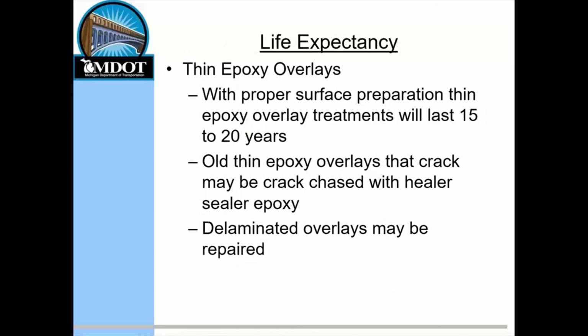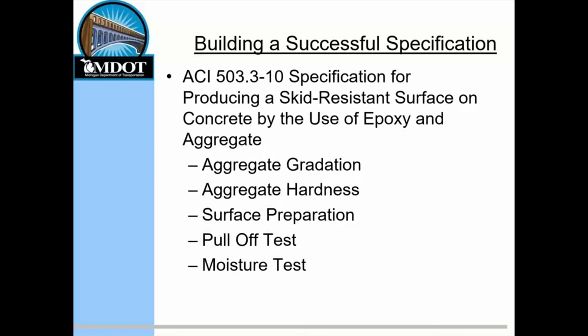The life expectancy of thin epoxy overlays with proper surface preparation, because surface preparation is everything, is 15 to 20 years in Michigan. Some of our older thin epoxy overlays may have some cracks in them. You can repair those by chasing them with a healer sealer epoxy. You can repair delaminations. And then at the end of life, when it's fully polished or the snowplows have removed enough of it, we're having a lot of success with milling off the old thin epoxy overlay and replacing it with another one. We really like our specification in Michigan. It pretty much guarantees that we're going to get 15 to 20 years of life.